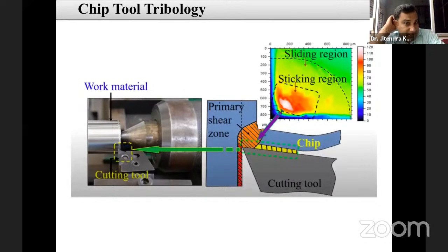When we analyze that surface from the thermograph, the IR camera, here you can see this is the cutting tool, and we performed a turning operation. There is the primary shear zone, and this is the chip-tool interaction. In that chip-tool interaction, you can see the crater wear happened a little away from the tool tip, most probably at the end of the sticking zone, where the sliding starts. These are the two zones. You can see that the sticking zone is a bit rougher than the sliding zone, and near the tool tip it is very hot compared with the sliding zone.